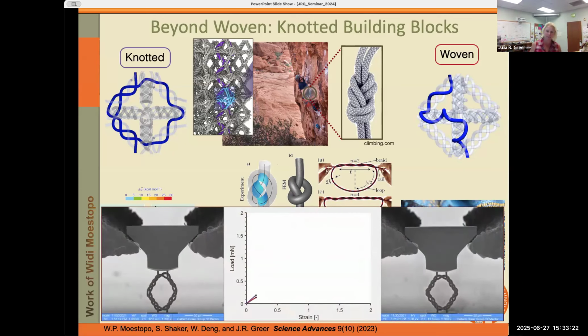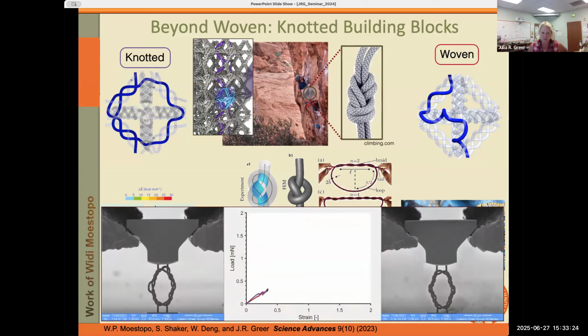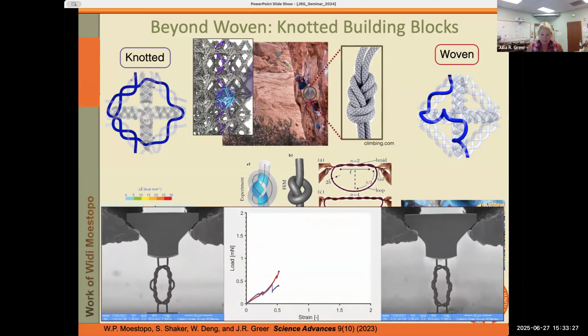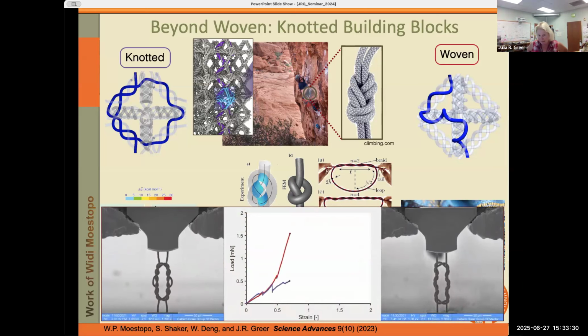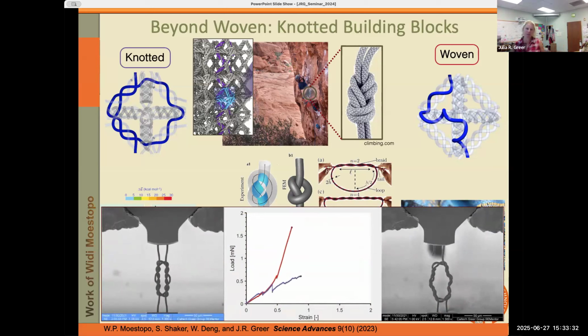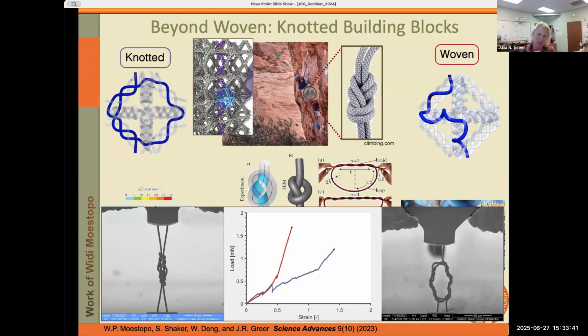So the knotted one is on the left, the interwoven one is on the right, and you can very clearly see that they first start deforming in exactly the same way. And after that, the regular one just becomes very stiff because we're starting to strain it, whereas the nano-knotted one shifts into the friction-dominated regime where we're effectively working against the friction force and tying the knot. So this taught us that at the nanoscale, we actually have a novel energy absorption mechanism available to us, specifically tying the nanoknots. And so you can see, as the area under the curve, of course, how much more energy we're able to absorb here.